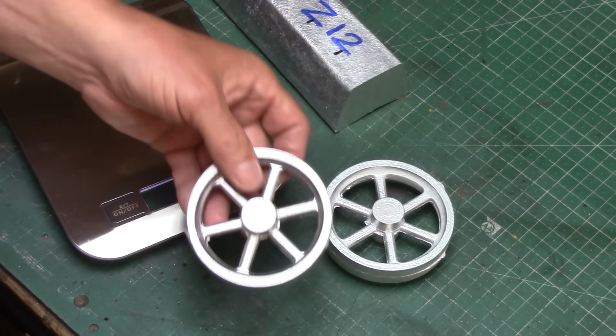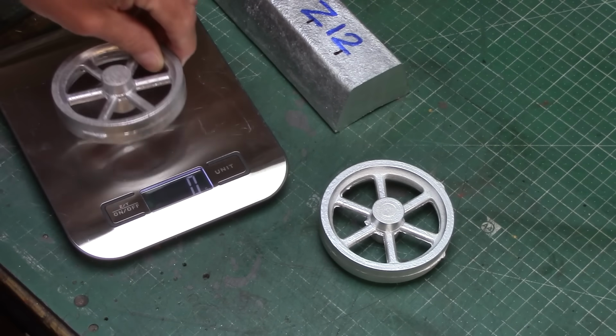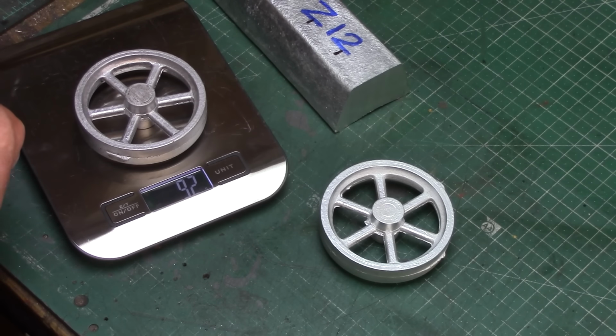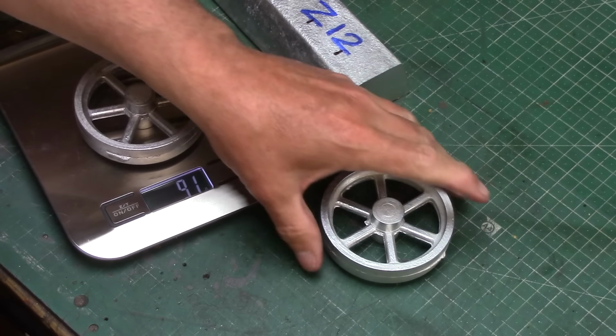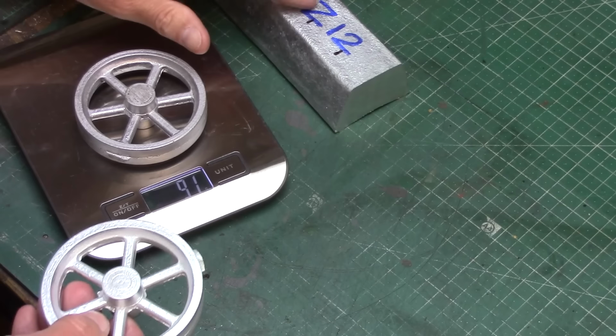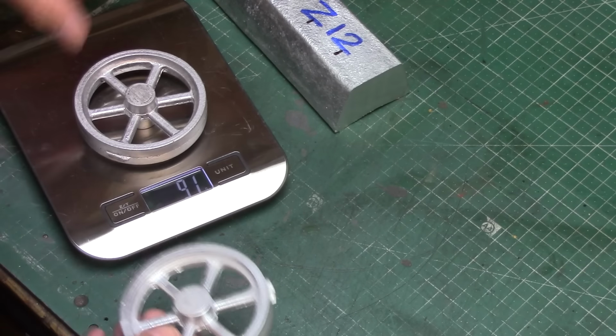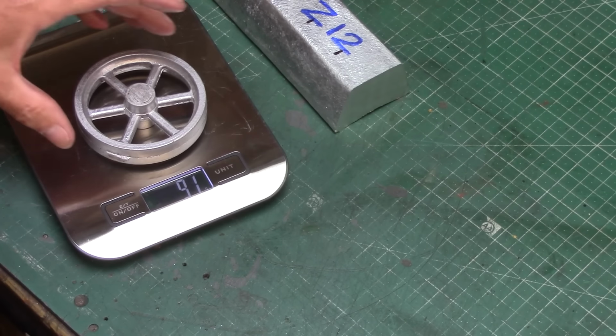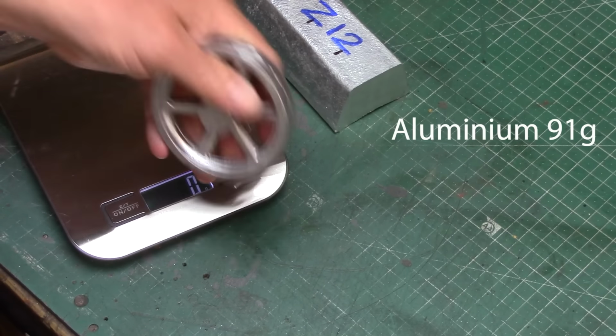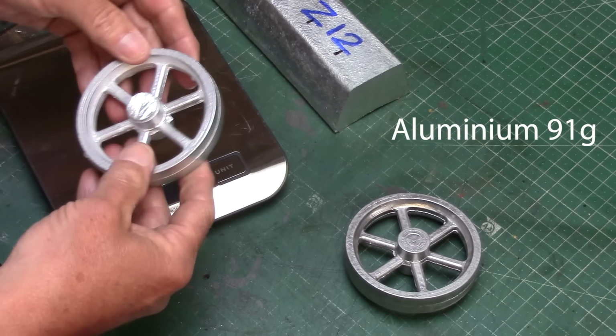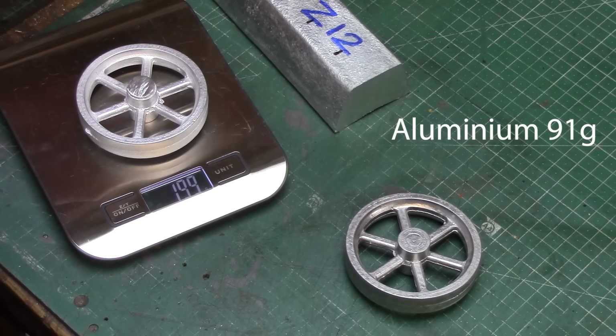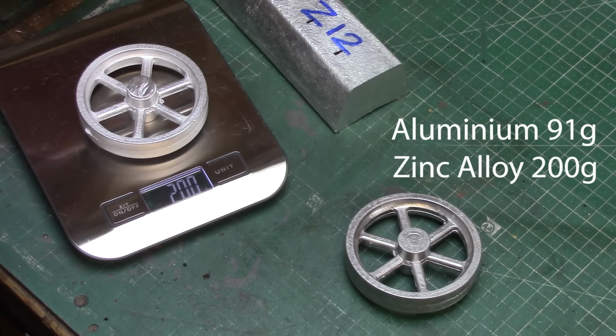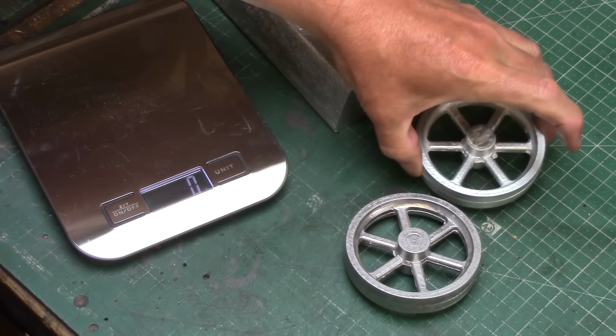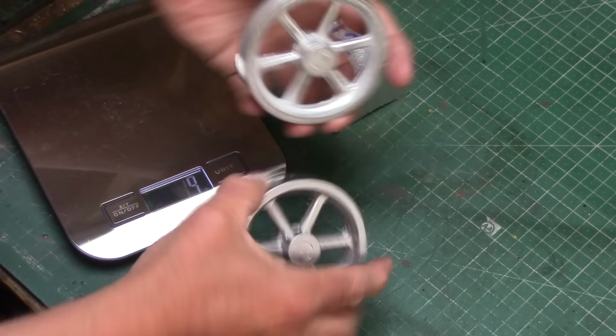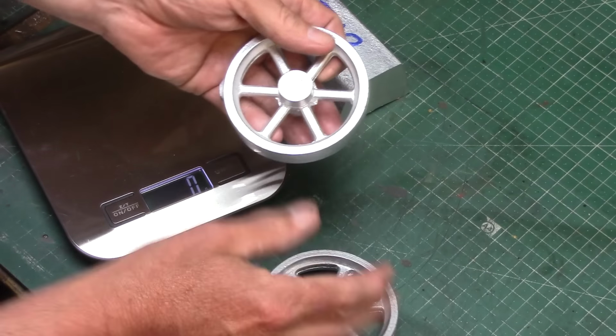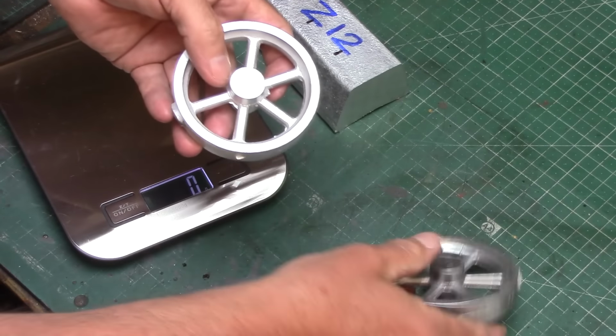Well, that was the end of the video, but during the course of the editing, I did get the opportunity to cast one of these flywheels with the zinc alloy, and as you can see there, that is 91 grams, and that is the aluminium one, and this is the zinc alloy one, and it is 200 grams, absolutely perfect. So that's at least double the weight of the aluminium flywheel, and you can really feel quite a difference actually. So yeah, nice metal to use.